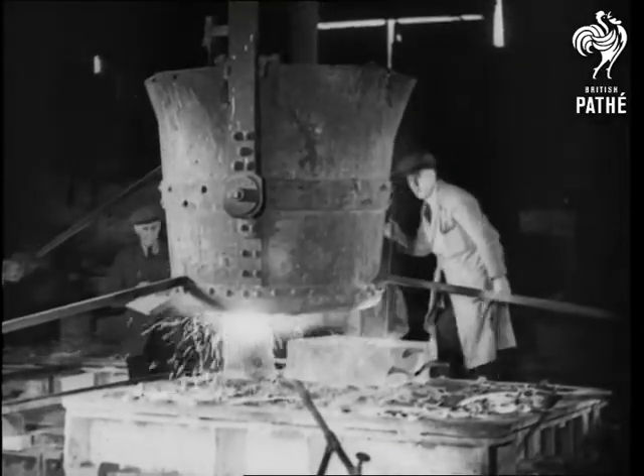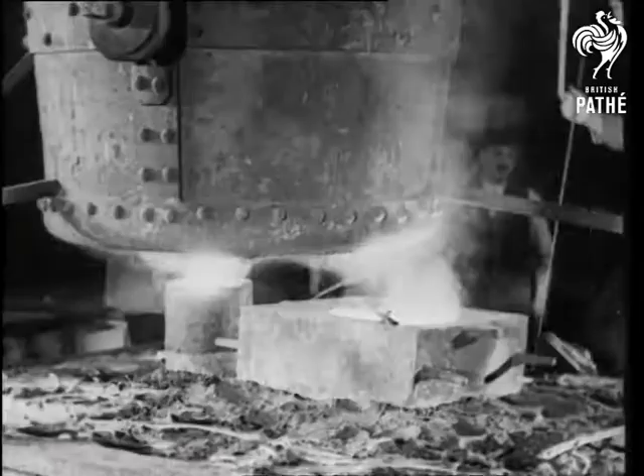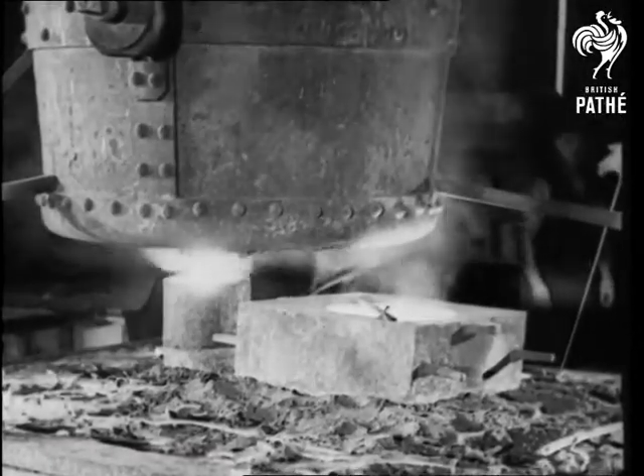After being baked for ten hours to harden them, the moulds are filled with white-hot metal. When filled, a further supply is poured in through a special reservoir, as a safeguard against rapid shrinking.